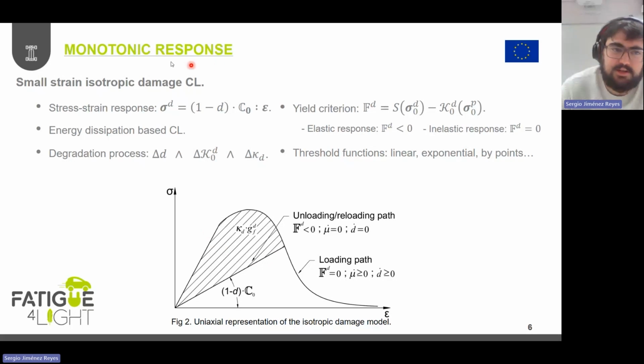And in this case, I'm presenting here this basic isotropic damage constitutive model, where this stiffness degradation is controlled by this scalar parameter, this internal variable called damage internal variable, which ranges from 0 to 1, 0 corresponding to virgin material state and 1 to fully damaged state. This constitutive model is, again, energy dissipation based constitutive model. So the deterioration process, the degradation process is being described according to this dissipation process of the fracture energy.